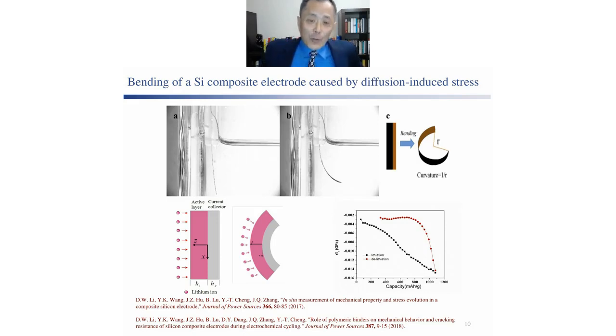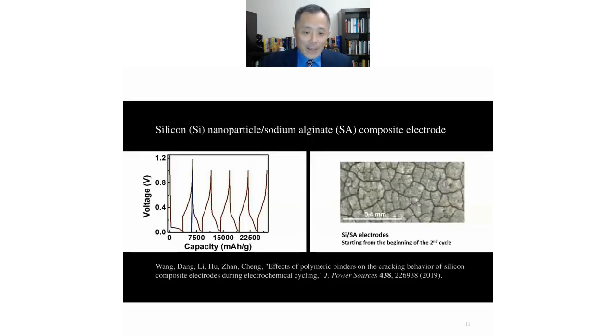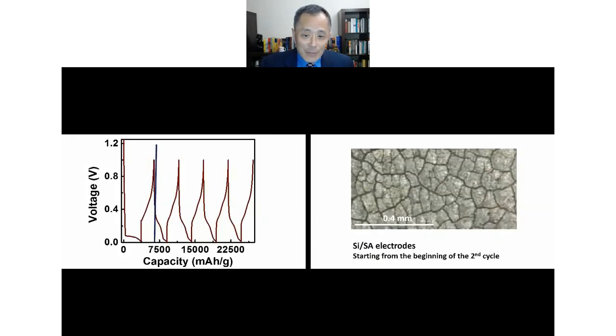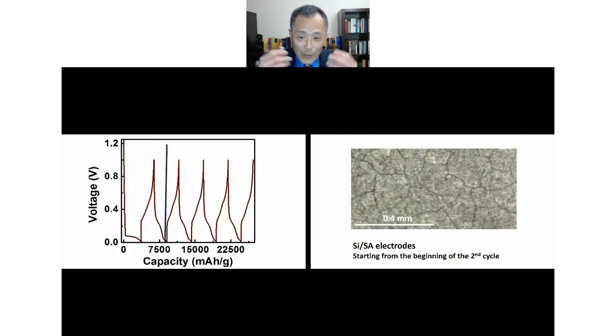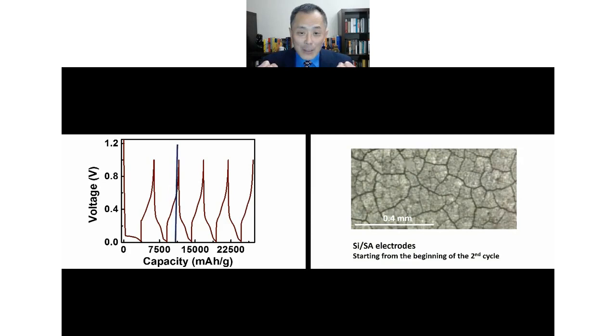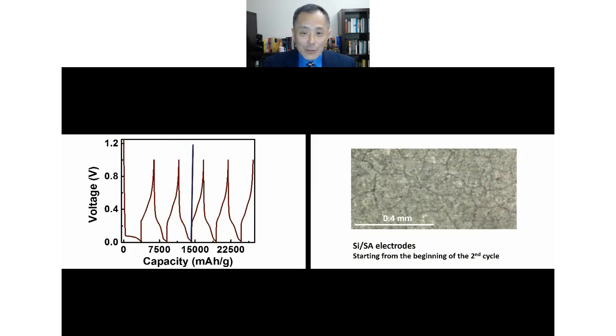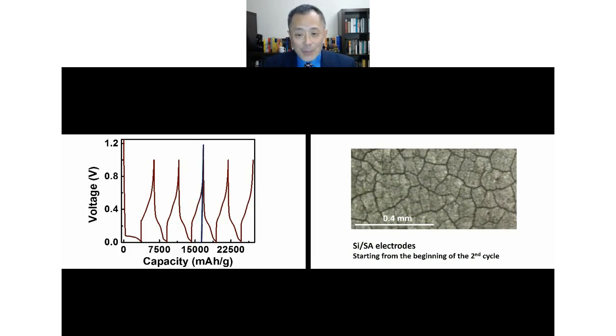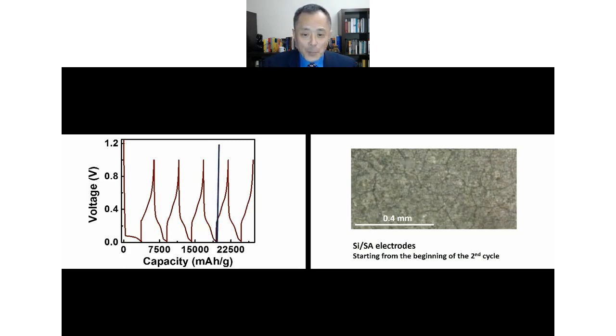Not surprisingly, therefore, electrodes can crack, as shown in this video. Showing here is lithium going in and out of the electrode. As lithium comes out, the electrode will shrink, causing the cracks to open up. And as lithium enters the electrode, the volume expands and closes the cracks. And this process can be repeated for many, many cycles.